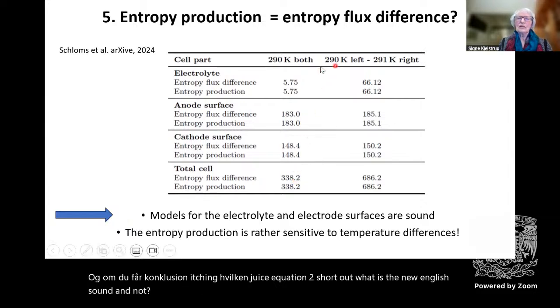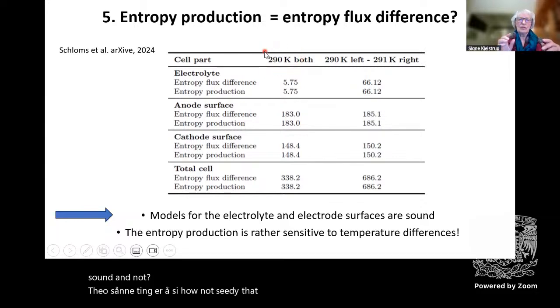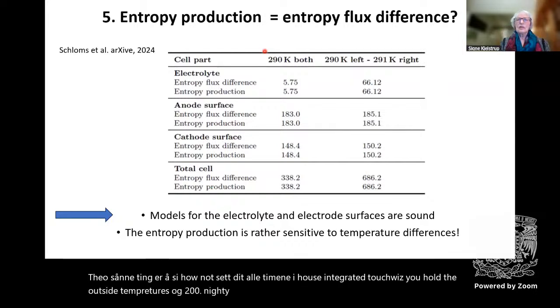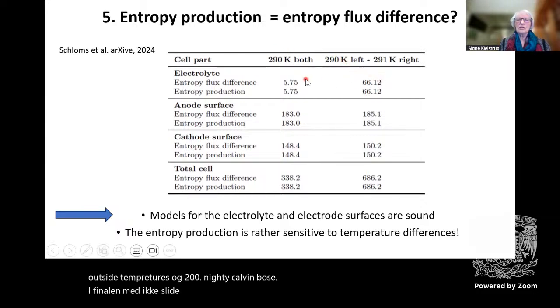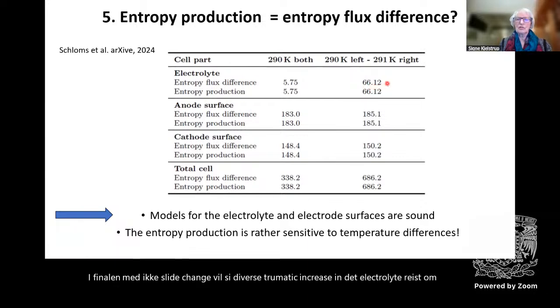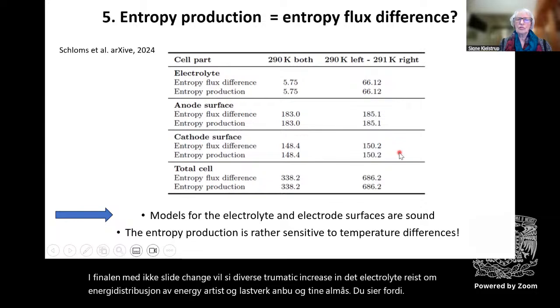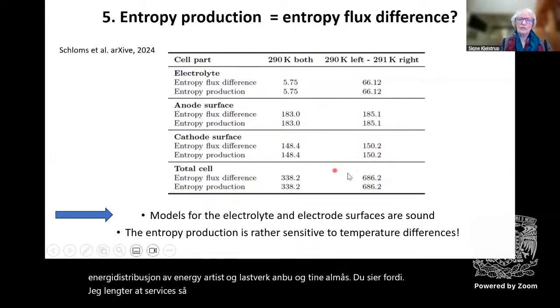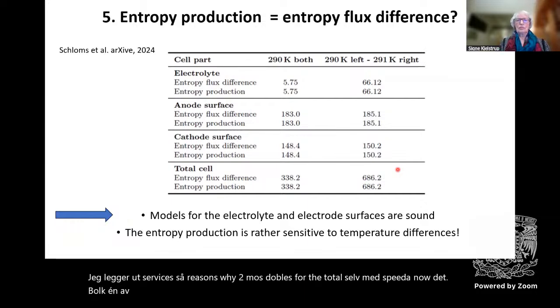But we see also something else. I have not said it, but all the time when I have integrated that across, I have held the outside temperatures at 290 Kelvin both. But if I now make a slight change, you see there is a dramatic increase in the electrolyte waste of energy, dissipation of energy, that is, or lost work. And you obtain almost the same for the electrode surfaces. So the reason why it almost doubles for the total cell must be that now the bulk anode and cathode count. So here we have a tool to examine really how the cell is losing work in operation.